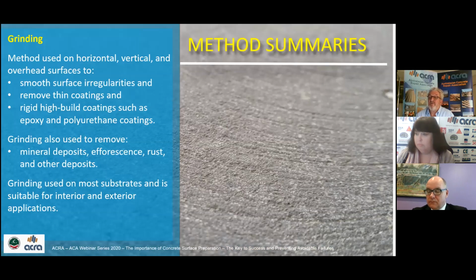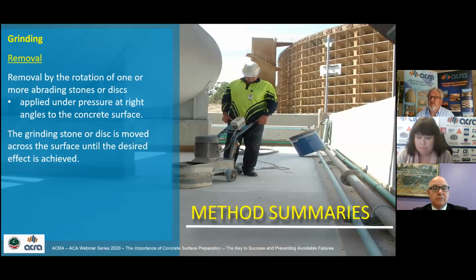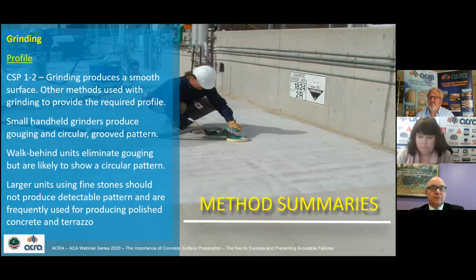Grinding is a method used on horizontal, vertical and overhead surfaces to smooth slight surface irregularities and remove thin coatings and rigid high-build coatings such as epoxy and polyurethanes. Grinding can also be used to remove mineral deposits, efflorescence, rust and other deposits. It is used on almost any substrate, interior and exterior. Removal is accomplished by the rotation of abrading stones or discs applied under pressure at right angles to the concrete surface. The grinding stone or disc is moved across the surface to achieve the desired effect.